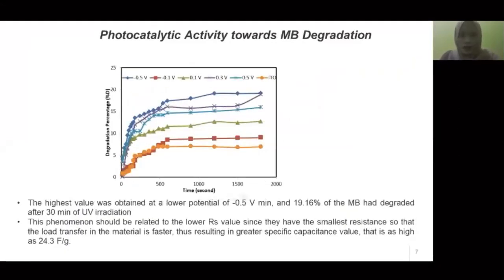Next is photocatalytic activity towards methylene blue degradation. From the figure, we can see that the highest value was obtained at the lower deposition potential of minus 0.5 volt, and 19.16% of the methylene blue had degraded after 30 minutes of UV irradiation. This phenomenon should be related to the lower RS value, since it is the smallest resistance, so that the charge transfer in the material is faster, thus resulting in a greater specific capacitance value, as high as 24.3 farad per gram. And next are the conclusions.